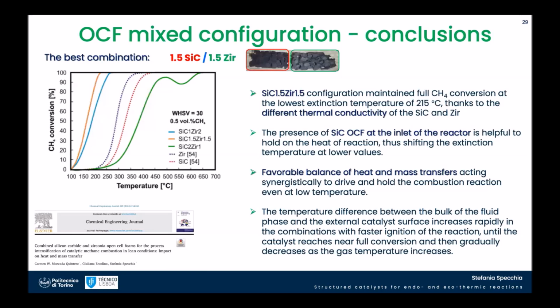So, on this concept study that we performed on the mixed configurations, here you can see the half and half configuration, and those are the single zirconia or the single SiC. By mixing the two supports, we were able to enhance very much the performance of our system. And this is thanks to the different thermal conductivity of the two supports.